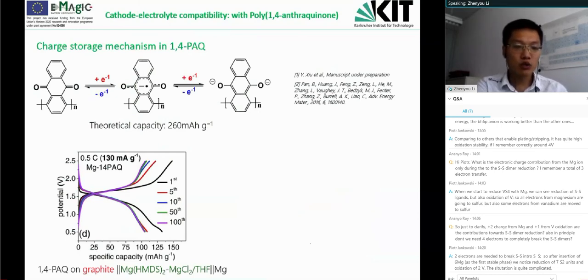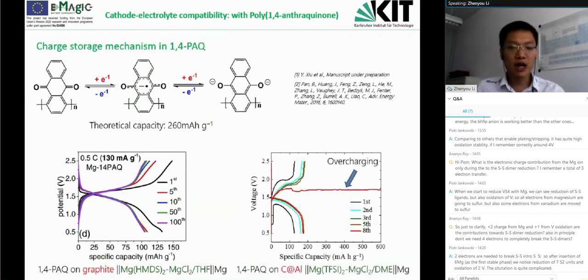On the other hand, we also noticed that they have used the graphite as the current collector. The reason is quite simple. Graphite is more anti-corrosive than the normal aluminum foil. So we also did a comparison study by using the chlorine-based electrolyte coupled with this PAQ cathode, but we have used this carbon-coated aluminum as a current collector.